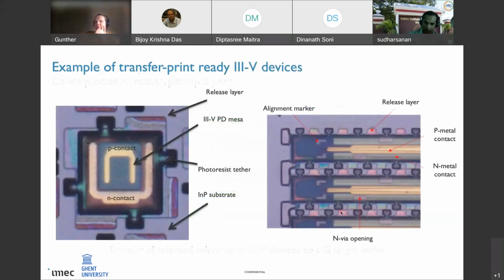So here you see an example of III-V components that are ready to be transfer printed. This is a microscope picture from the III-V source wafer. So what do we see on the left-hand side? This is, for example, for a photodiode. You see a very simple PIN mesa structure here. These dark structures here, those are the tethers. In this case, this is implemented using photoresist. And this colorful layer here is the sacrificial layer that is being etched. So this is during the etching of the sacrificial layer. After the sacrificial layer etching is finished, you get freestanding PIN photodiode structures here on a III-V substrate.